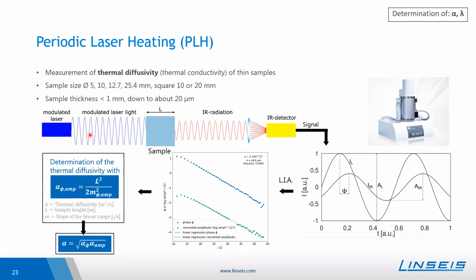The main difference is that we use a modulated laser with a certain frequency, and because of that, also the infrared radiation emitted at the rear surface of the sample will be also a thermal wave with the same frequency as the modulated laser light. This we also collect with the infrared detector, and in the end, the signal will look like that. The I_L curve symbolizes the modulated laser light, and the second curve, the I_IR, is the signal of the sample. The frequency is the same.